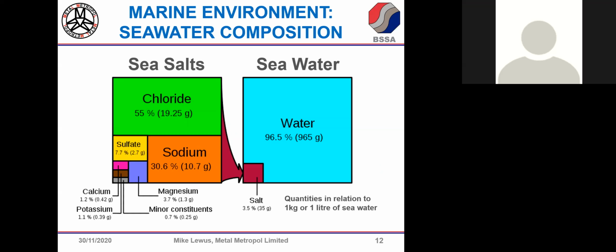Those salts are obviously very significant because the conductivity of seawater goes up, and corrosion is driven by electrochemistry, by electrochemical reactions. And if the conductivity goes up, the corrosion currents go up. So reactions that are at the base of corrosion are actually driven harder just because of that conductivity. To put it in perspective, deionized water has a conductivity about 1/1,000,000th of seawater. Tap water varies to 100 to 1,000 times less conductive than seawater.